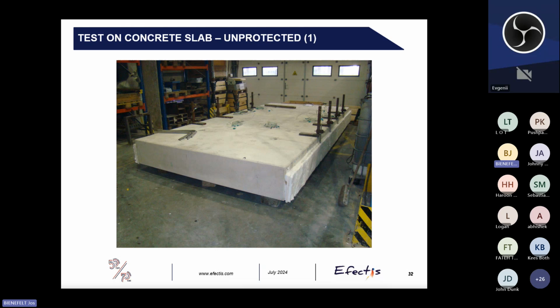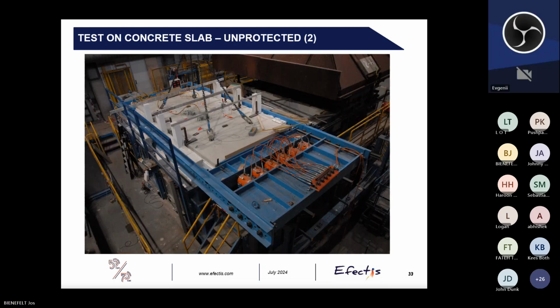Next up is an example of a test on a concrete slab, and in this case, an unprotected concrete slab, so no PFP was installed. This slab has a length of 5 meters and a width of 2.4 meters and a thickness of 40 centimeters. The heated area had dimensions of 4 meters by 2.4 meters, and the slab was only supported at the ends. The slab was installed on our large fire resistance furnace, and a compressive stress was induced in the slab using this blue loading frame. And for this test, a 10 megapascals compressive stress was used.